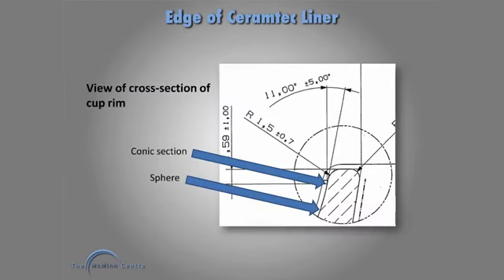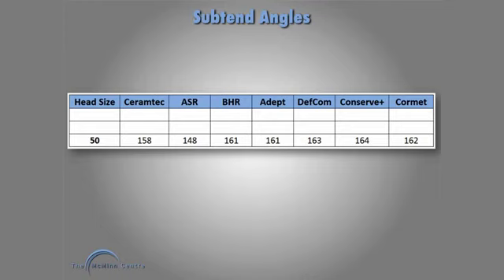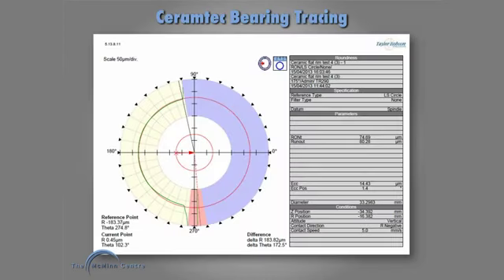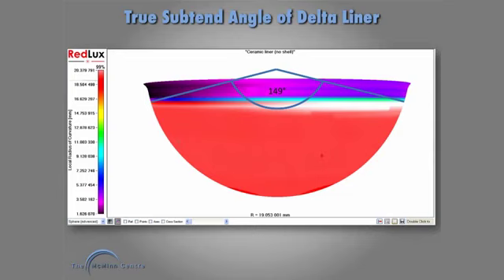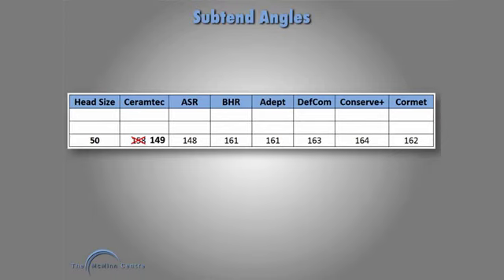From the drawings of the Ceramtec liner, there's a spherical portion on the articular surface, which then turns into a conic section, which then turns into an edge radius. And from the drawings, you would anticipate that the subtend angle of this Ceramtec liner is 158 degrees, but actually it's not. There's a roundness tracing, and the green line shows the edge and the acetabular articular surface and the edge again, and it's well short of the 180 degree mark, which is the straight vertical black line. When you do redlux on this, what you find is that the spherical section and the conic section are blended together, and the true subtend angle is actually 149 degrees. So not 158, 149. So the ASR was 148, this Delta Liner is 149.